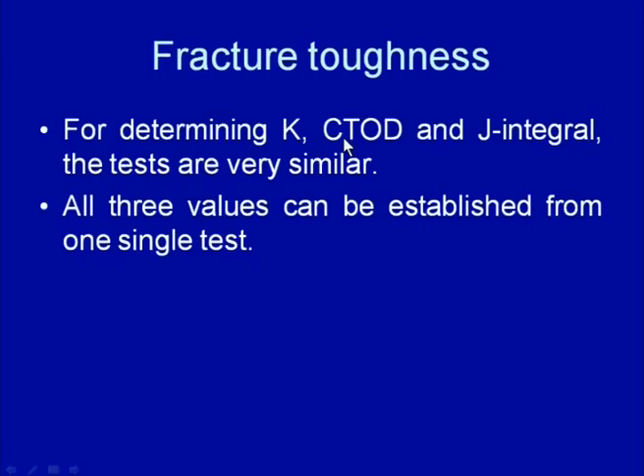So, for determining the K, CTOD, that is crack tip opening displacement, stress intensity factor, and the J integral, the tests are very similar, and all three values can be established from a single test. Whether they are valid or not, to check the validity separate calculations are made.